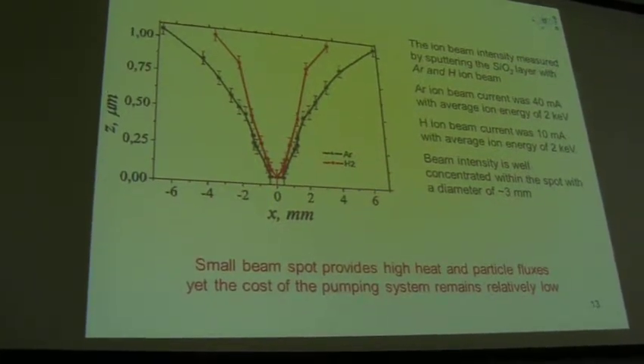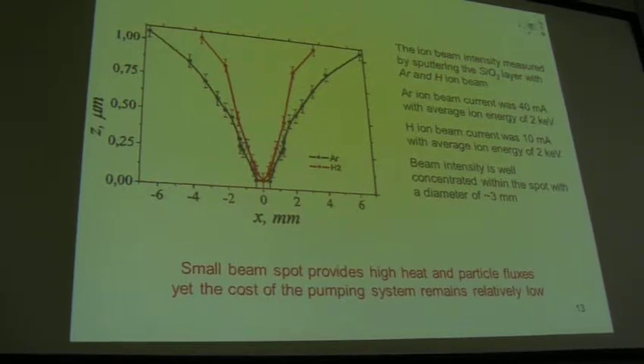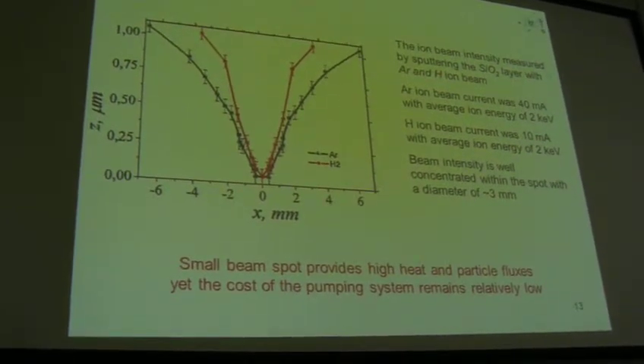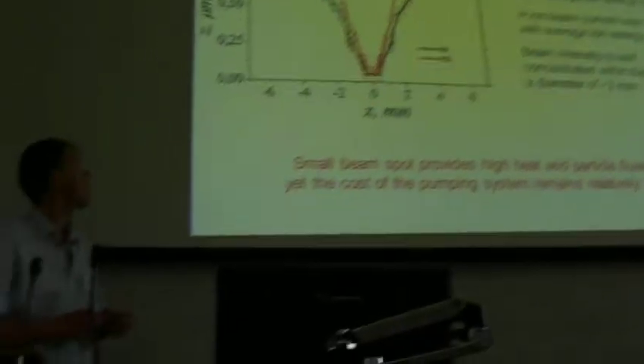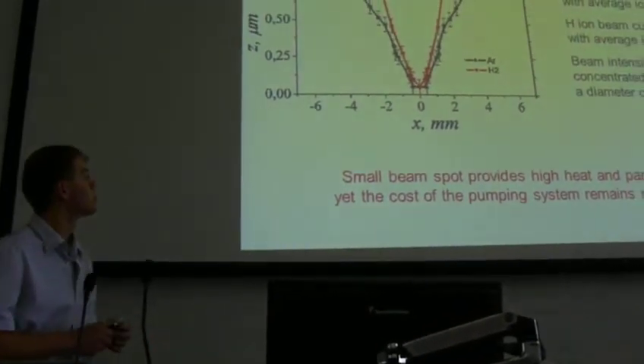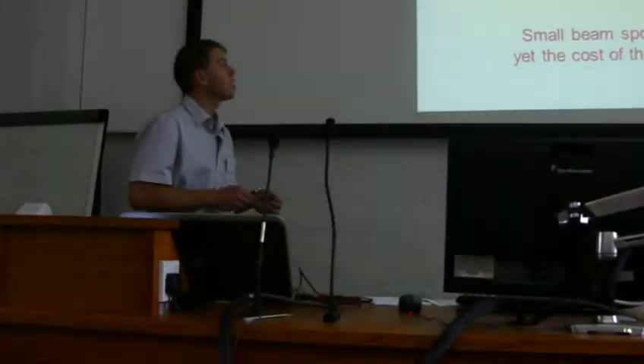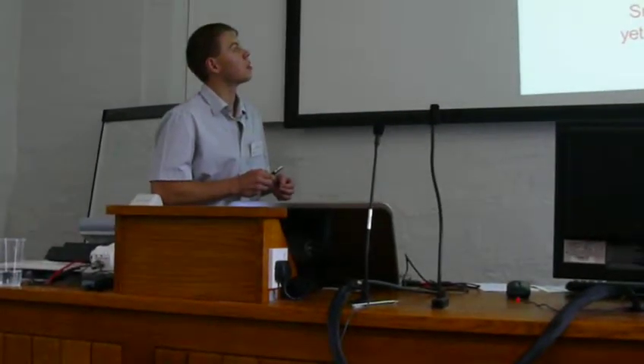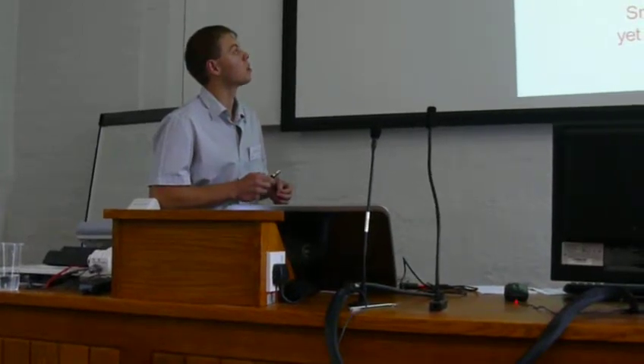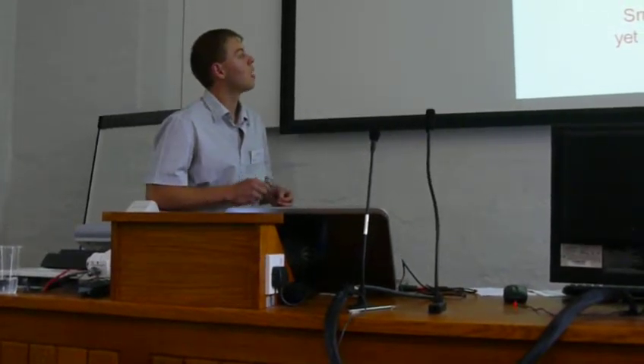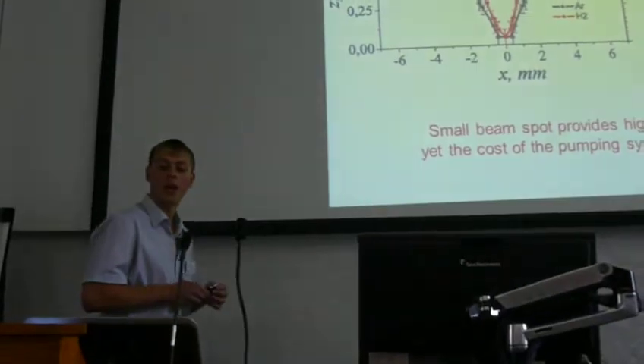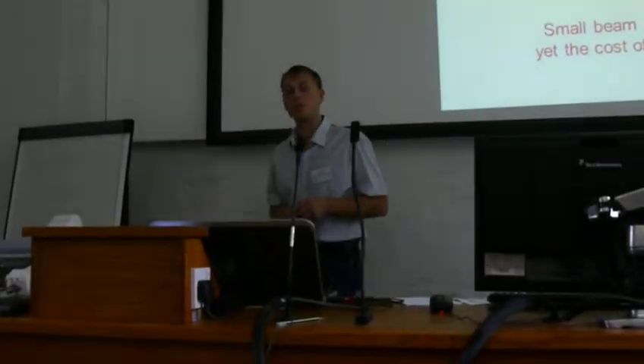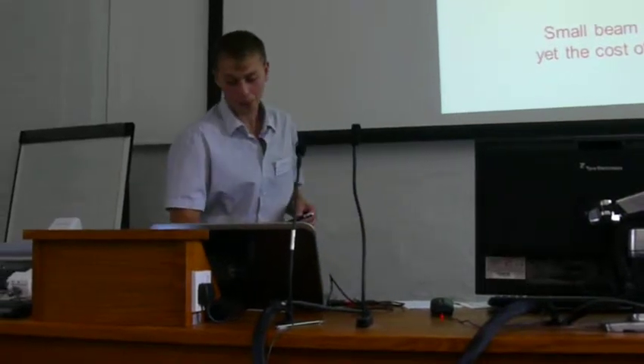The ion beam intensity was obtained via sputtering SiO2 layers on a Si wafer by hydrogen and argon ion beams. One can see that the beam intensity is well concentrated within a spot with a diameter of nearly 3 millimeters. So, a small beam spot provides high heat and particle flux, yet the cost of the pumping system remains relatively low.